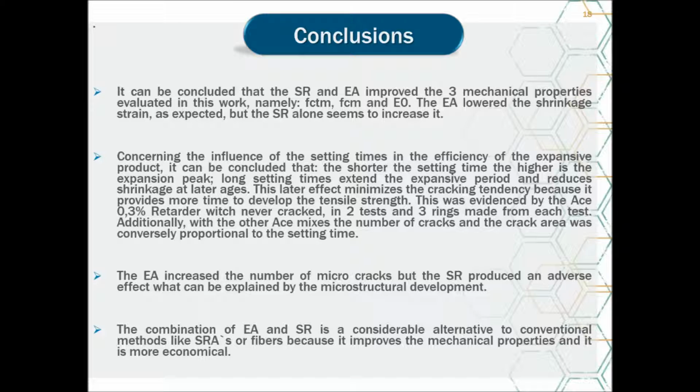Concerning the influence of setting times on the efficiency of the expansive product, it can be concluded that the shorter the setting time, the higher the expansion peak. Long setting times extend the expansive period and reduce shrinkage at later ages. This latter effect minimizes the cracking tendency because it provides more time to develop the tensile strength.